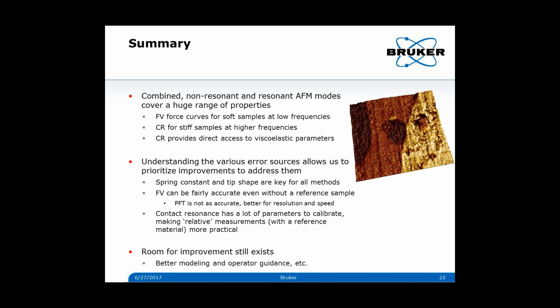Force volume force curves are great for soft samples at low frequencies, and that's the best tool for the soft samples. Contact resonance for stiff samples. And then contact resonance is also giving us direct access to the viscoelastic parameters, whereas if you want to do that with force volume, you need to apply one of those models that's more complicated and less common, we'll put out there.